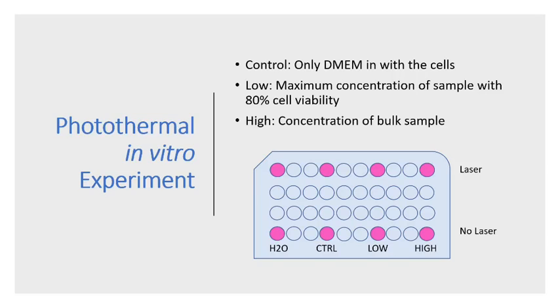What we have here is the lowest concentration we used of our sample. That low concentration is the same concentration that gives us 80% viable cells. The high concentration is what we used in the photothermal properties experiment, so when we were originally figuring out the temperature change, that's the high concentration. We also chose to irradiate the top row with the laser, and the bottom row we did not, so we could compare a laser-irradiated cell with one that didn't get the irradiation.